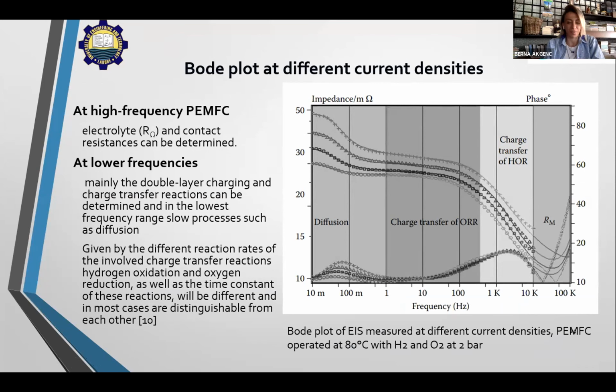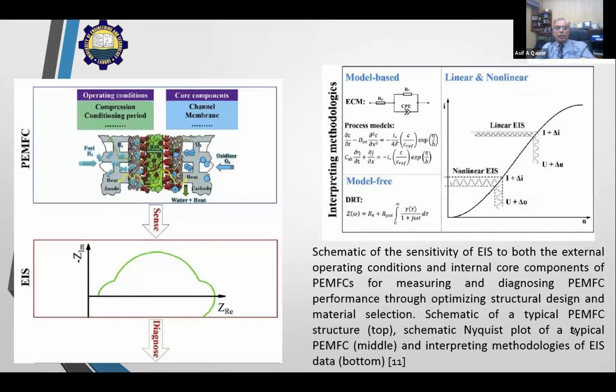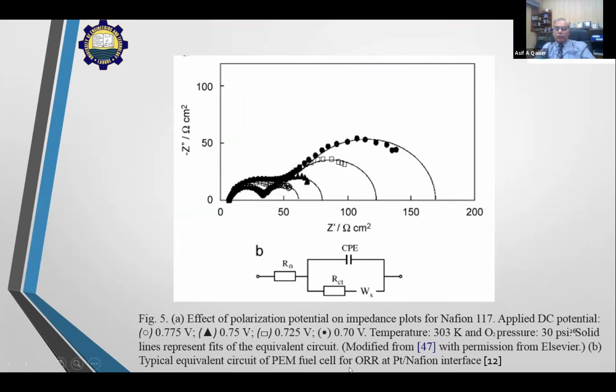So sensitivity is there, where we can have a Bode plot for hydrogen oxidation reaction and oxygen reduction reaction, at very low frequency, 10 millihertz. We have diffusional processes. This is actually at different current densities, so the curves are well resolved for different current densities for a fuel cell. Similarly here, this is another representation for different DC potential, polarization potential on impedance of Nafion. So again, we have sensitivity. We represent this behavior with this equivalent circuit, and as we change the potential, we have a change in the shape and also the magnitude or size of the semicircles.